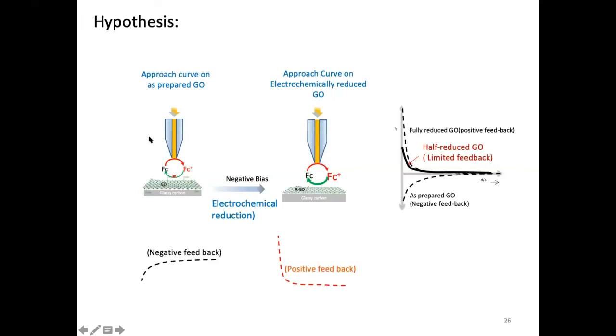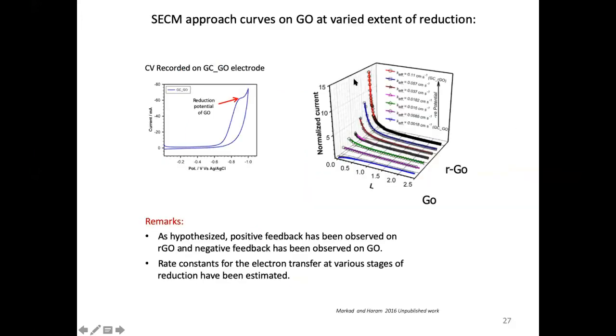Yes, by SECM. What we did, you know, the whole game is we measure the feedback on graphene oxide before polarization. My hypothesis is, if it is not polarized, I get negative feedback. If I polarize and form reduced graphene oxide, I should get positive feedback. And if I get in-between electron transfer, I will get in-between limited feedback. That's what happens in the actual experiment.